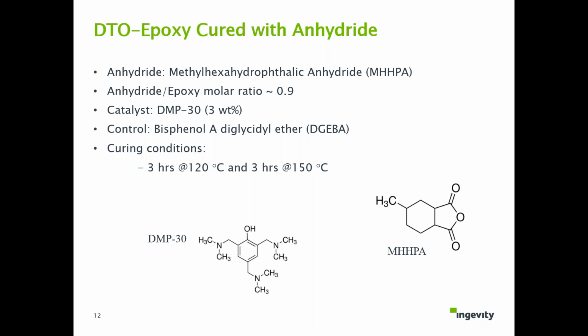The second part I'll talk about is DTO epoxy cured with anhydride. The anhydride we use here is MHHPA, as shown by the structure at the bottom. The molar ratio of anhydride to epoxy is 0.9 to 1. We're also using 3% of the catalyst DMP-30. I also show you the structure on the bottom part. This catalyst is also called K54, or people also call it Ancamine. It's a commonly used catalyst for epoxy curing.